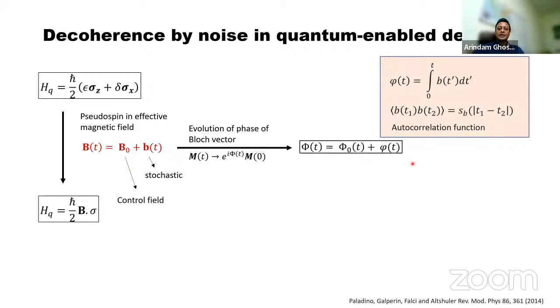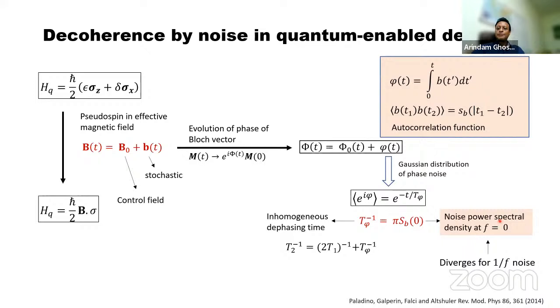That stochastic part can be shown to be essentially the stochastic component of the effective magnetic field, which gives rise to the autocorrelation function. And if I look at exactly the same mechanism, the overall quantum information stored in the qubit decays with time, with a time scale of capital T phi, where capital T phi is set by the noise power spectral density at zero frequency. Now imagine if you have 1/f noise in your system, then at zero frequency, 1/f noise diverges. Of course, you cannot go to absolutely zero frequency, but there is a very, very large component in the dephasing of the quantum information that comes because of the large noise present in the system at low frequencies due to 1/f noise. So as a result, what we need to do is find ways of reducing 1/f noise in materials and systems and devices so that they can be used as coherent systems in quantum applications.